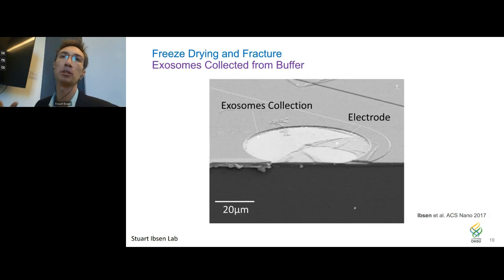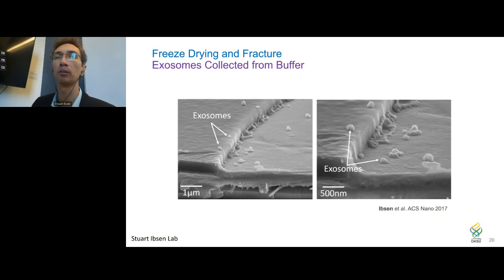Now, we were able to actually look at the particles themselves as they were collected. We've got here those same glioblastoma exosomes that were put into a buffer so we could see them very easily and then collected on the chip. We freeze-dried the chip and then snapped it in half so that we could look at them in a zoomed-in fashion. You can see here the electrode itself in sort of an angled view on the SEM. And then when we zoom in, we actually see the particles themselves captured along the edge of the electrode, which is right here.